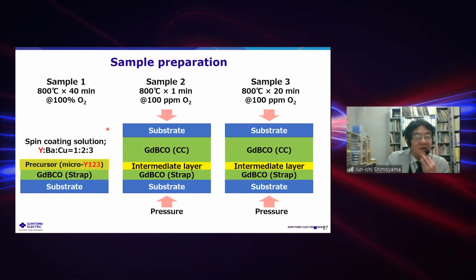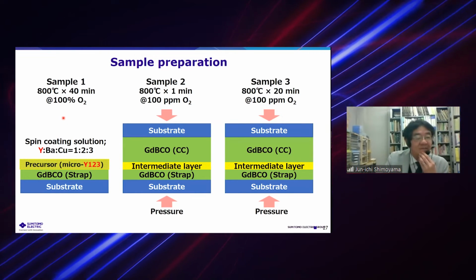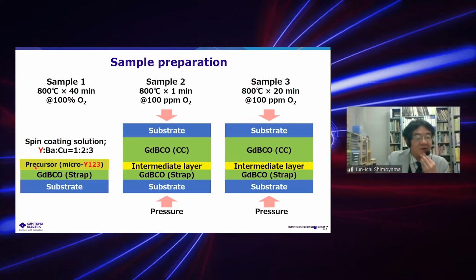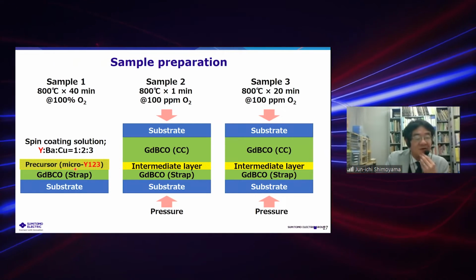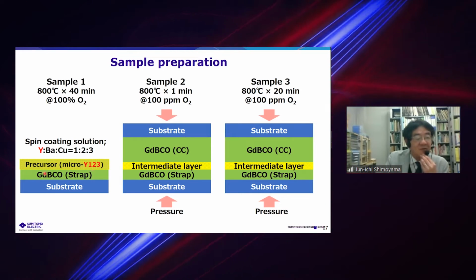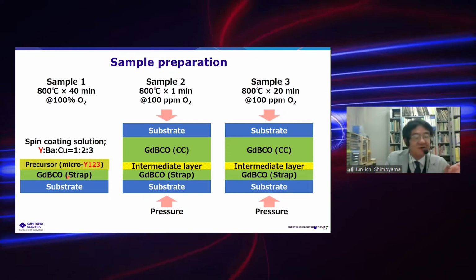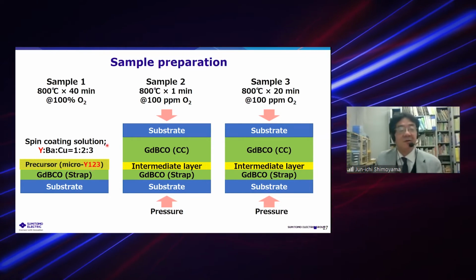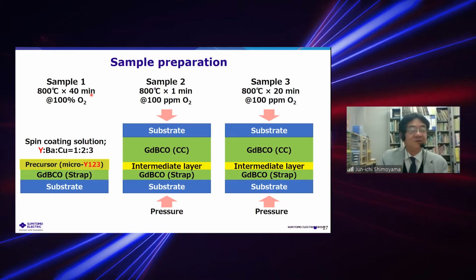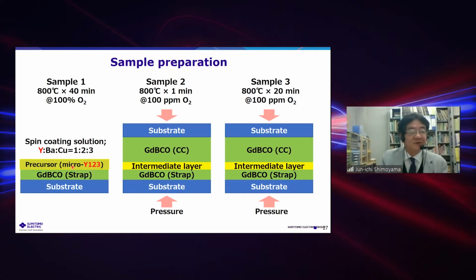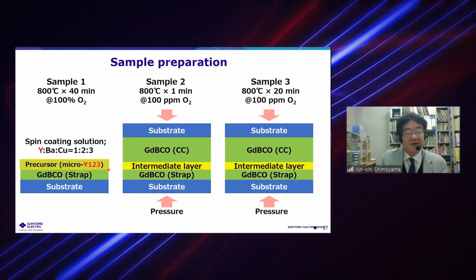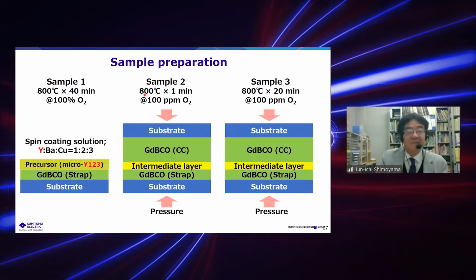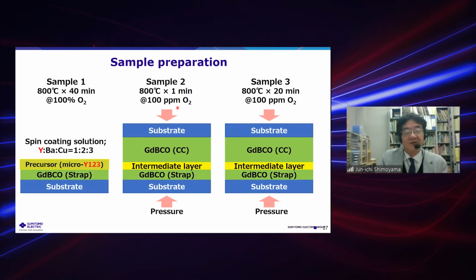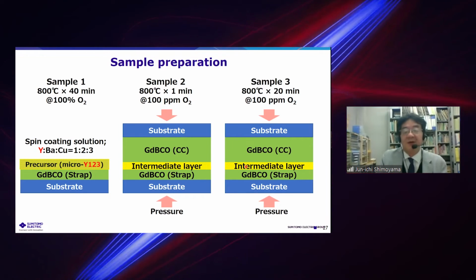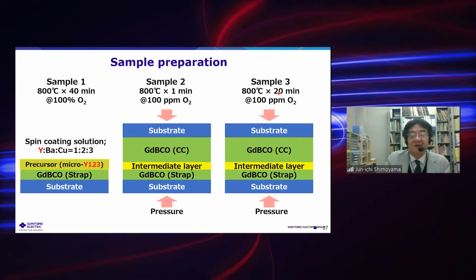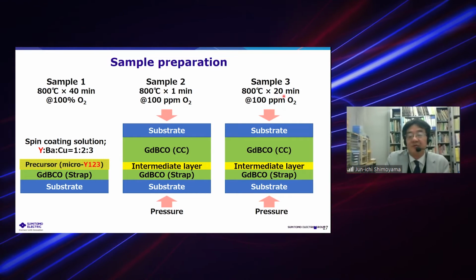So here I'd like to introduce briefly this method again. At the beginning, a precursor layer composed of microcrystals of yttrium-123 on the gadolinium-123 coated conductors. This is a joint piece, the joint strap. Sintering at 800 degrees C for 40 minutes in pure oxygen is important to prepare such precursor layers. Such a thick precursor layer shrinks by heating at 800 degrees C for 1 minute in a reducing atmosphere under applied pressure in this way. And then the sintering time is increased to 20 minutes.